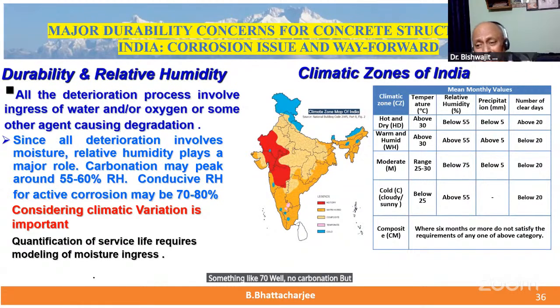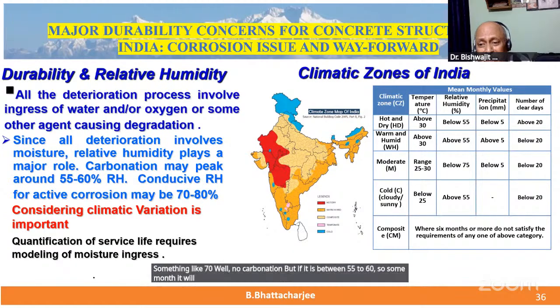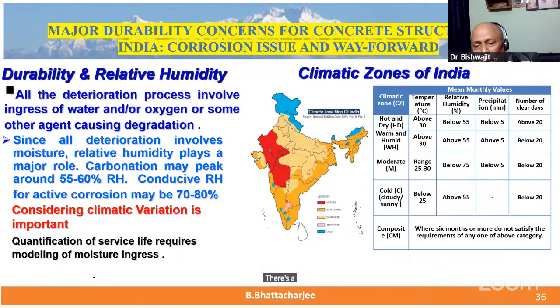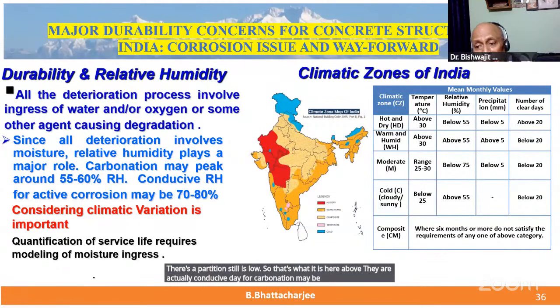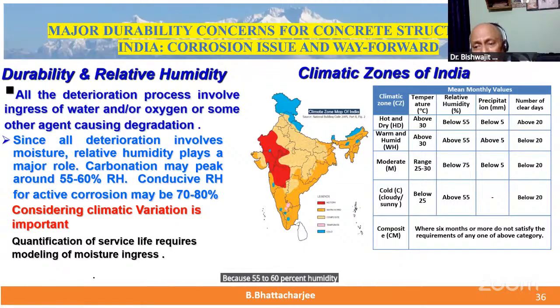But if it is between 55 to 60, some months it will be below 75, 4 months it may not be, but the temperature range is 25 to 30, that doesn't make much of a difference. Precipitation still is low. Here above 5, there are conducive days for carbonation, maybe somewhat more, because 55 to 60% humidity may last every day. During the monsoon season, it will be saturated. But after monsoon, for many days, it will be there. So it has to be looked into. At 50 to 70, you can say the carbonation occurs. We have not calculated for this, for moderate.